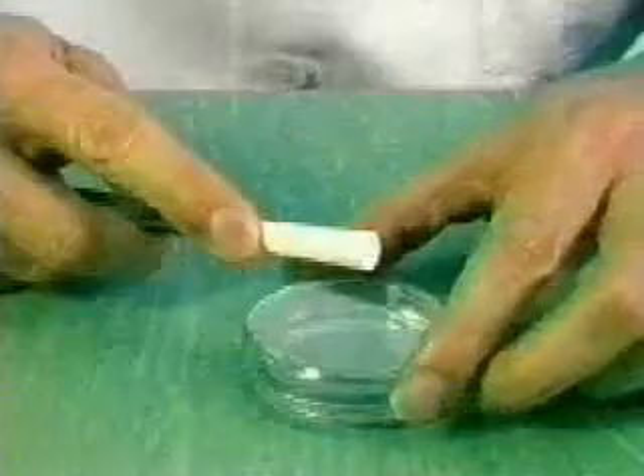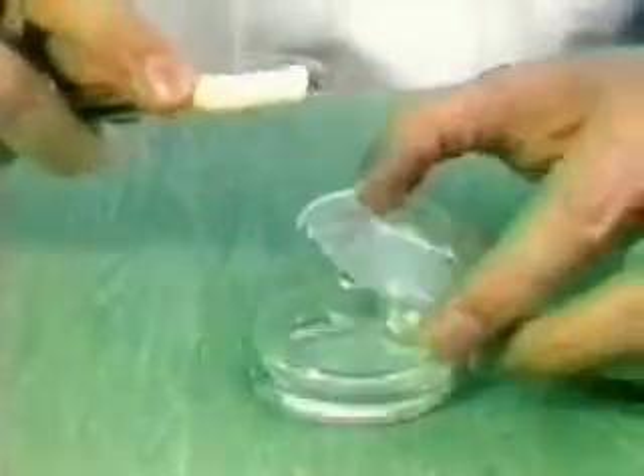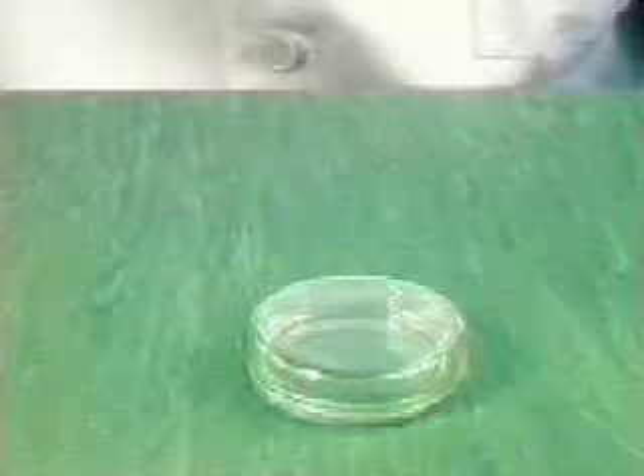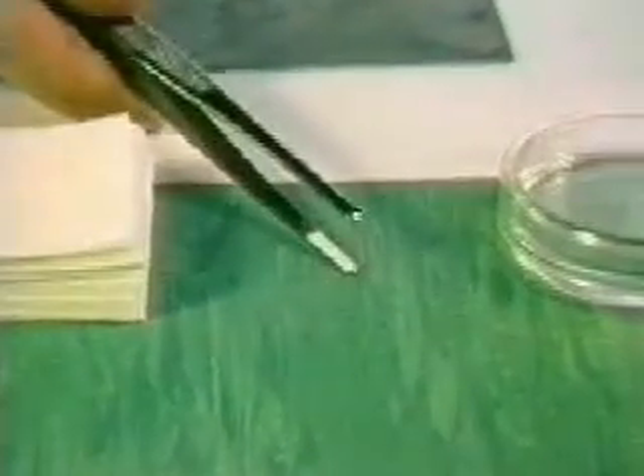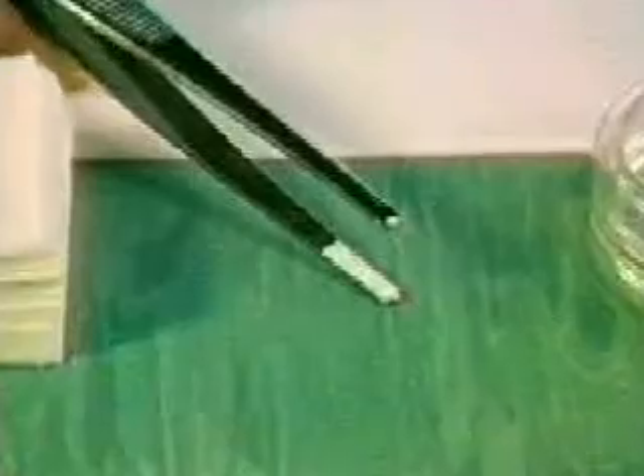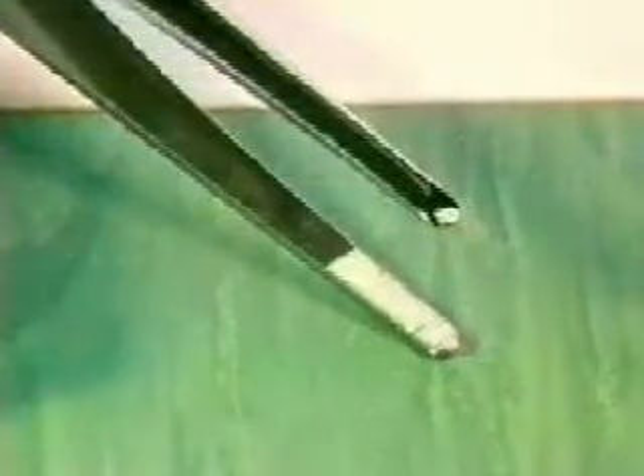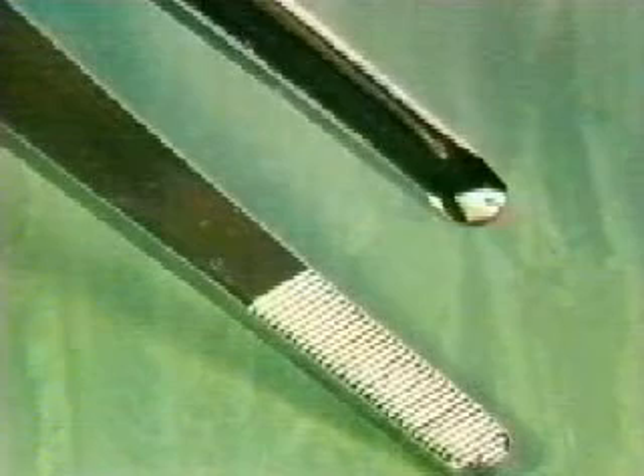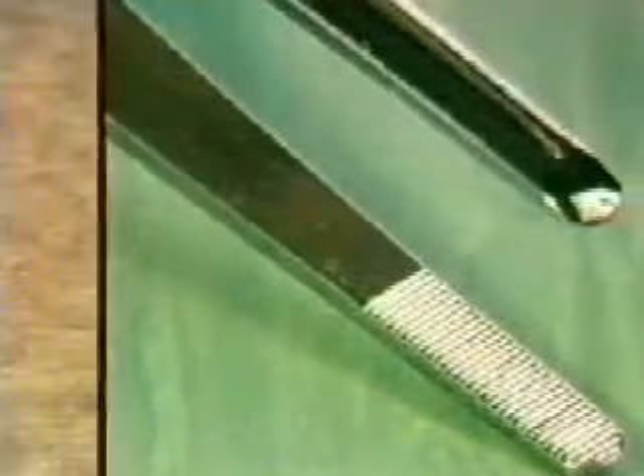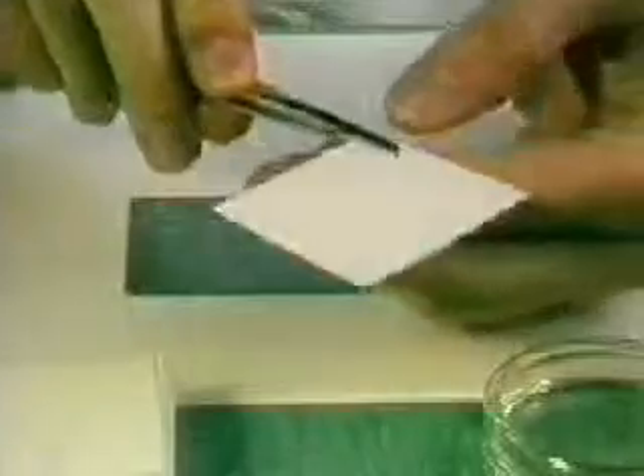First of all, coarse cleaning is carried out with a cellulose pad, which is wrapped around the tweezers and soaked in the solvent. This is how it can be done. Place a small pile of cellulose pads to hand. Use tweezers with rounded points to prevent injury. The pads have a grain which you can see if you hold the pad up to the light. Hold the pad with the tweezers in the direction parallel to the grain and roll it up.